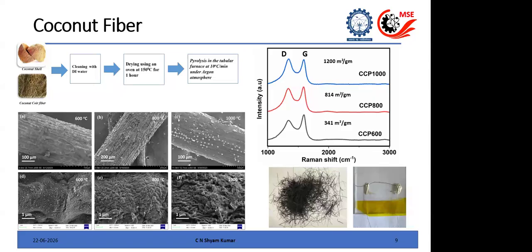Now we go to some examples, which we all know very well, the coconut coir. This coconut coir is one of the lignocellulose biomass which contains very high lignin content. So if you can take that and pyrolyze it. So this is an example where we took a coconut coir. These are coir, not the fiber, because this is after the retting process and all. So this is what we use for making coir, and they use some treatment to make it a bit hard and strong.